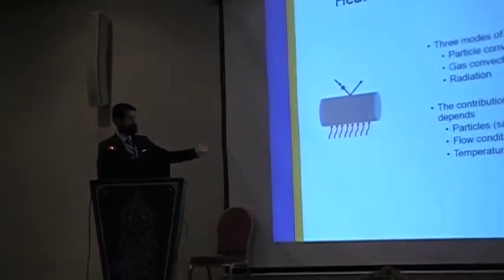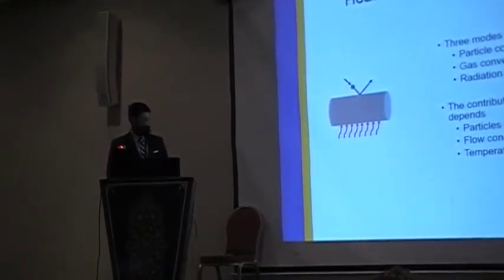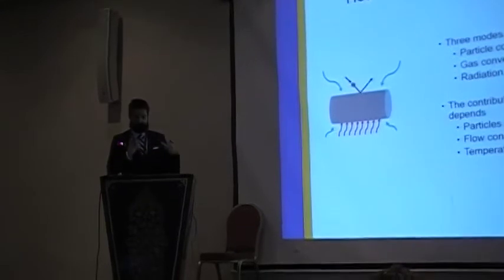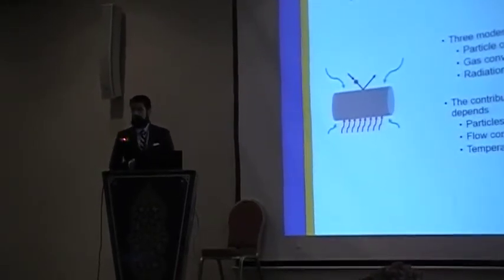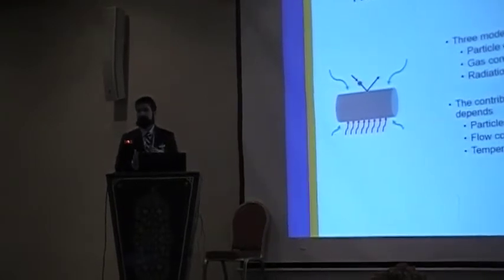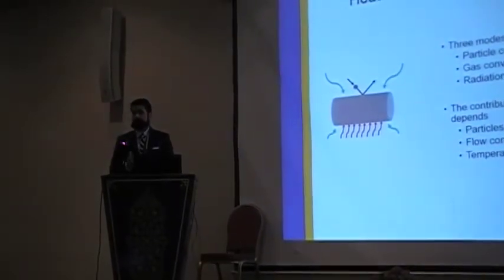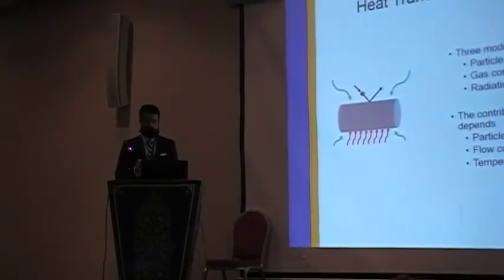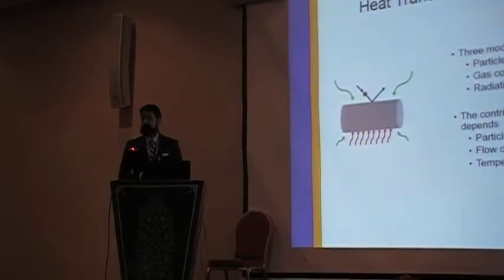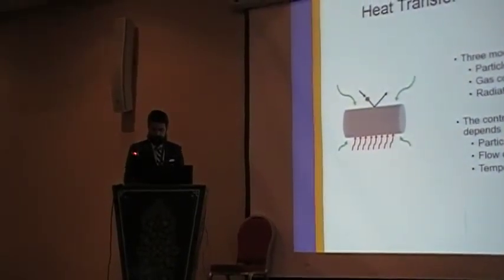So, heat transfer, which is the main thing that I'm here to talk about today. There are three modes of heat transfer that occur to an immersed surface in the fluidized bed. You have particle convection, which occurs in the thin gas lens between the particle and the surface itself. There's the gas convection, which is the standard forced convection that I'm sure we're all familiar with. And there's radiation, which occurs with the neighboring particles. All of these three can be summed to provide an overall heat transfer coefficient, but the contribution of each really depends on a lot of factors like the particles themselves, the flow conditions, and other parameters like temperature and pressure.